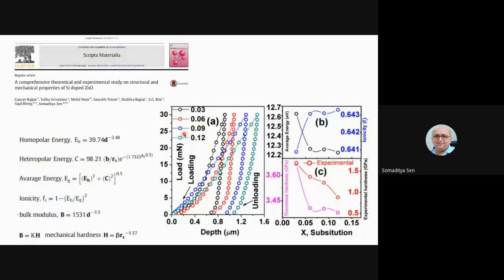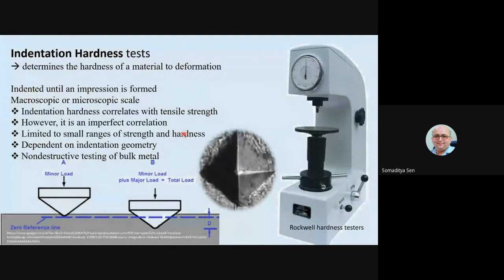Now, coming to the last stage of my talk, there are two or three techniques. Some of the work that is important right now, that I'm doing, partially started, not yet fully put my stress on, is the effect of pressure on the structure. You remember that I discussed that if the wurtzite structure is compressed, at maybe 10 gigapascal pressure, you can get into a rock salt structure. Now that has been experimentally proved.